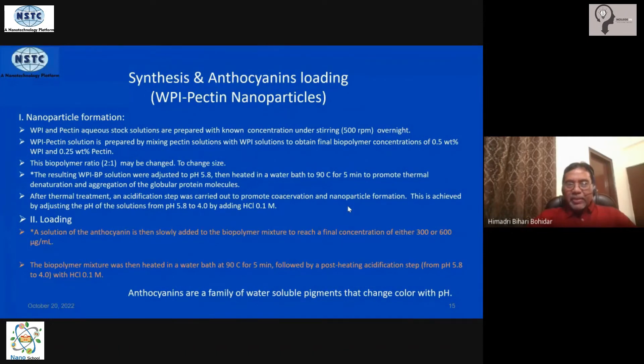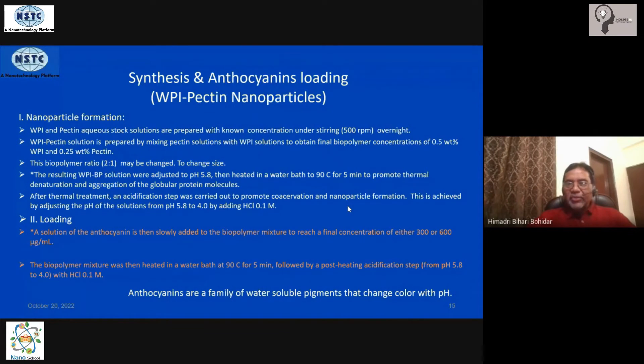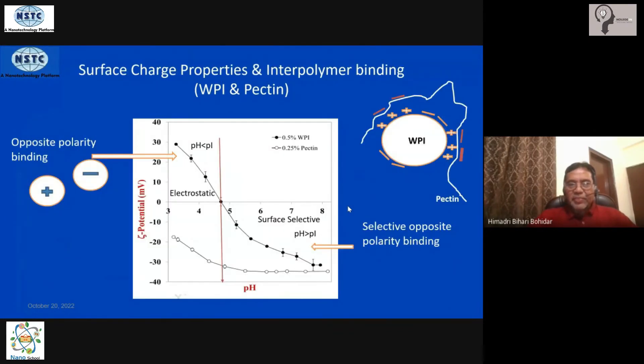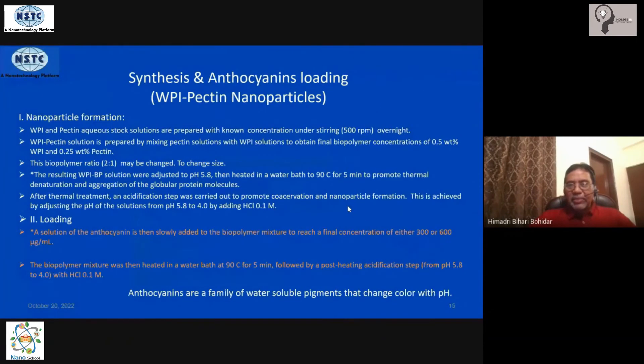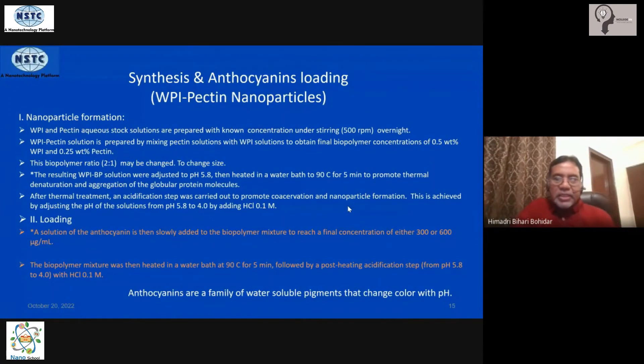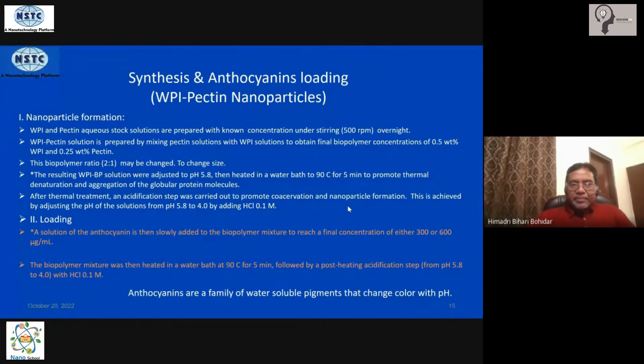After heating, the pH is changed from 6 down to about 5.8 or further down to 4.4. When you reduce the pH to 4.4, you are below the isoelectric point of approximately 4.8–4.9, allowing strong electrostatic interactions to take over. This is the acidification step — driving the pH into the strong electrostatic binding region causes nanoparticle formation. The nanoparticles are then separated from the solution and collected through filtration.